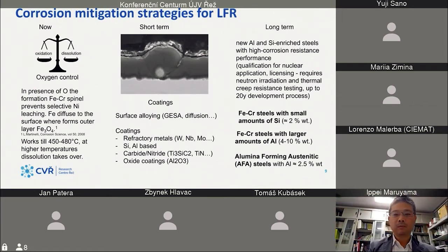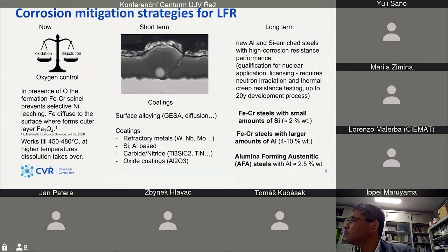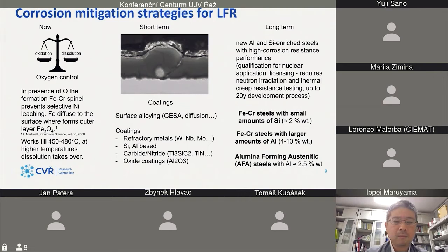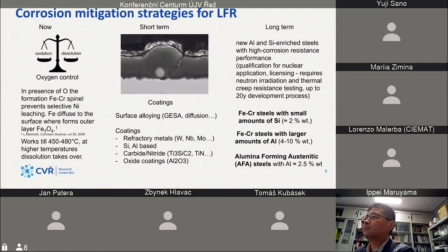Short term means that it's available right now, but not at industrial scale. So this strategy is based on coatings of known materials. That has one problem, because it's hard to guarantee perfect coating over the whole surface. Even a small defect can cause localized attack that is really problematic, for example, on fuel claddings.